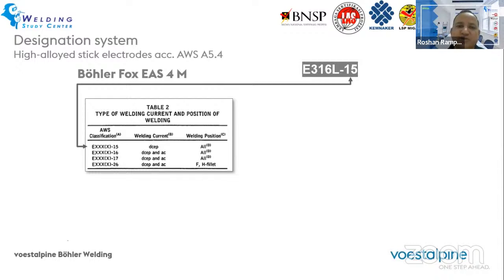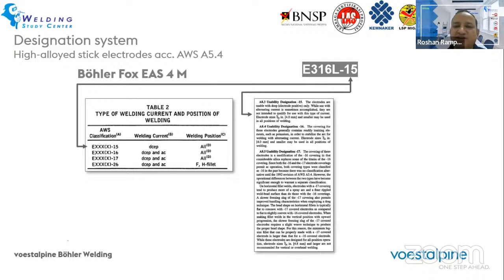Similarly, when we talk about stainless steel electrodes, the electrodes are classified based on the chemical composition, generally based on the steel base material which is suitable or matching with the chemical composition of the electrode. Then different coating types are classified based on their usability designation. Most common are -15, -16, and -17. -15 is a basic coated electrode, -17 is a rutile or acidic coated electrode, whereas -16 is in between. It is a basic rutile type in which there is a mix of basic as well as rutile flux components. So I have already explained to you the effect of selection of different types of coating for different stainless steel material.